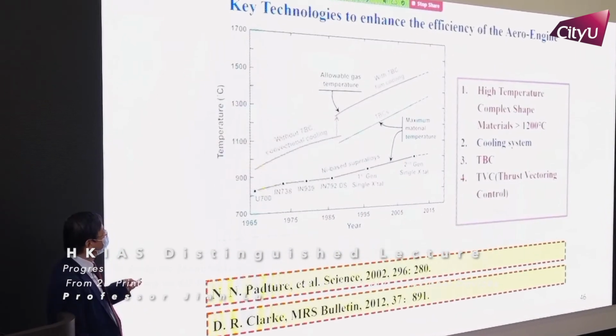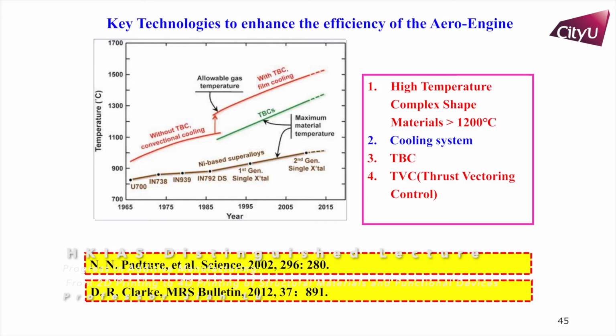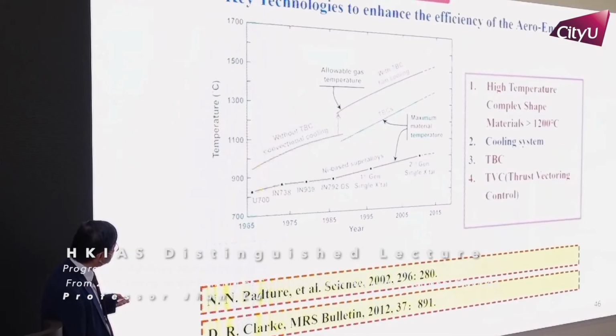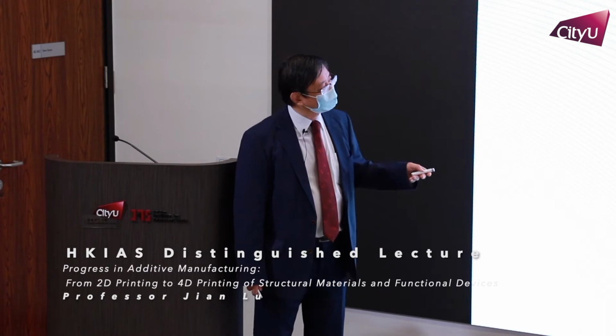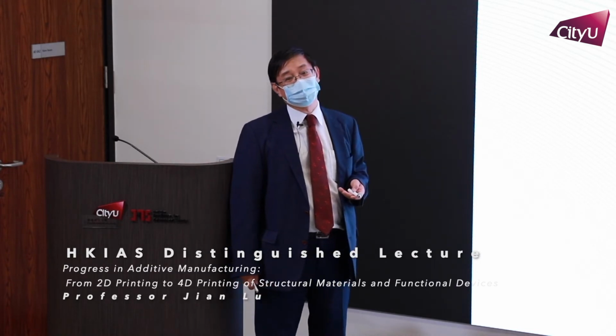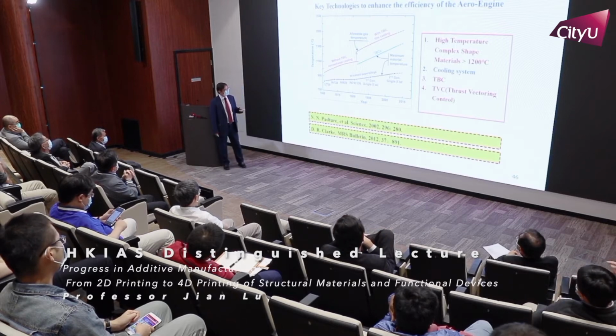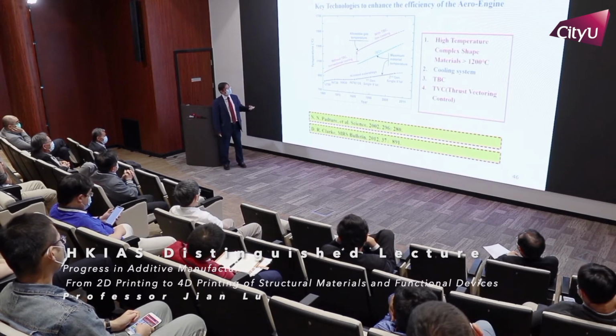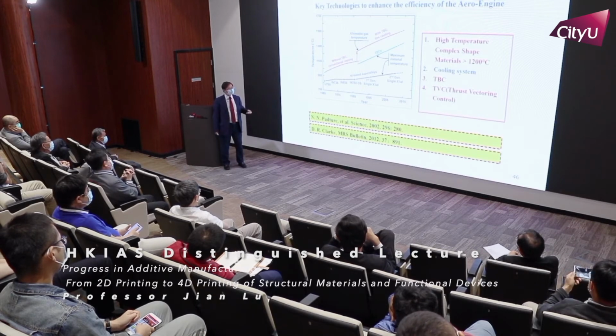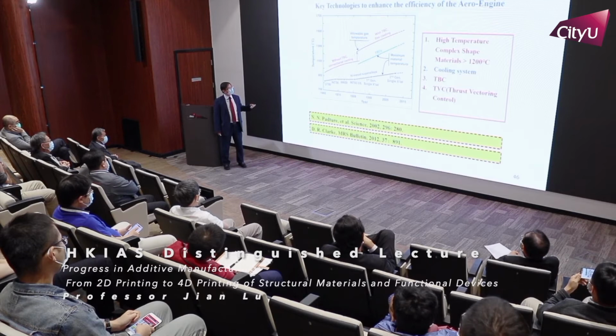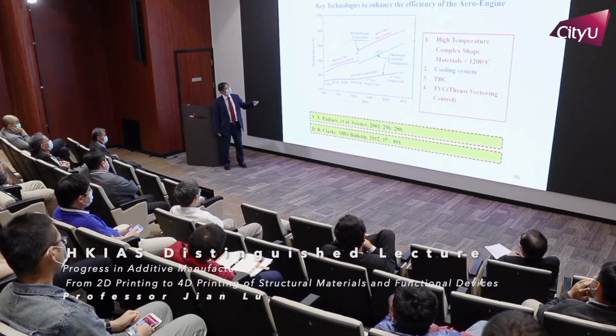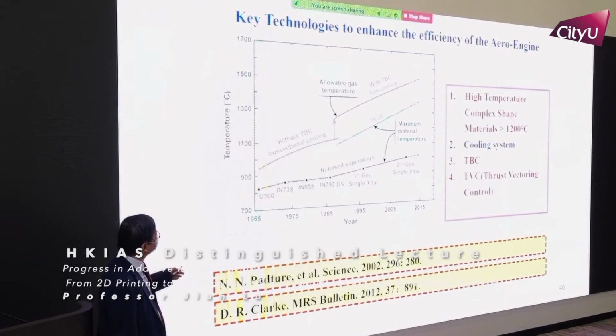So why do we need thermal barrier coating? As you see, Professor C.T. Liu worked on the superalloy. In more than 50 years, 55 years, we basically increased the working temperature by 150 degrees, okay? So it's a very small progress, but if we coat the structure, then the working temperature can be increased by 200 degrees. Then if we have a smart cooling solution, the working temperature can be further increased by another 200 degrees.